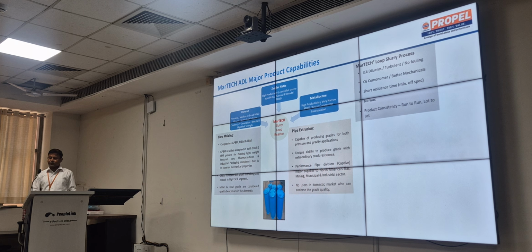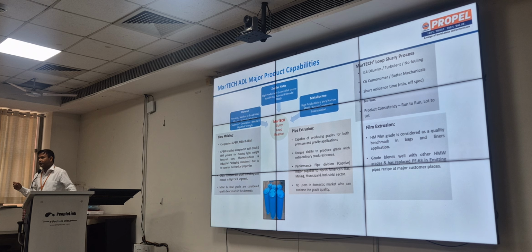In fact, the pharma bottles which are produced, all the 50 cc or 100 cc or 150 cc bottles, all the pharma applications, are also produced from the second CBF line. This is the only grade produced from the Chevron Phillips technology that is accepted globally. The domestic market also, for the US FDA, Canada FDA, the grade produced here is all based on these technologies. So with this technology, you can produce blow molding grades, which is also used in pipe extrusion. Film you can produce, but because of narrow molecular weight distribution, you are able to produce high molecular weight products. The performance in terms of processability and bubble stability is a challenge for the grades produced from these technologies.